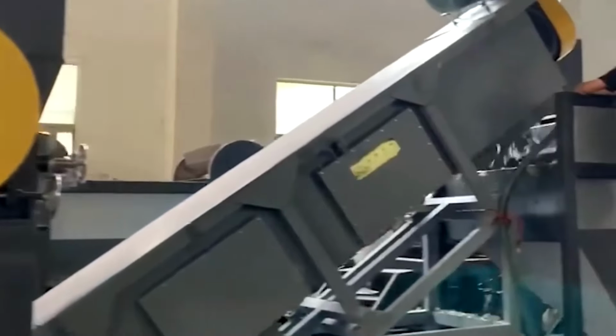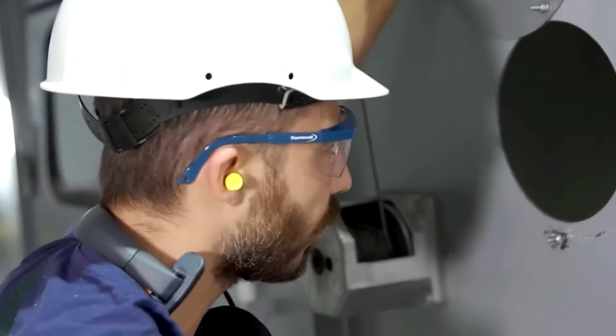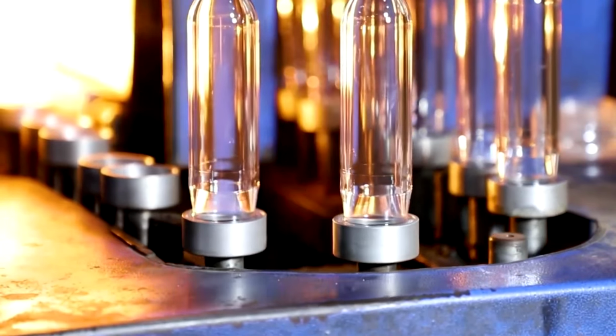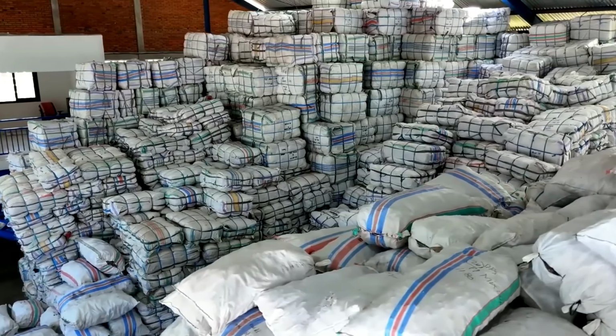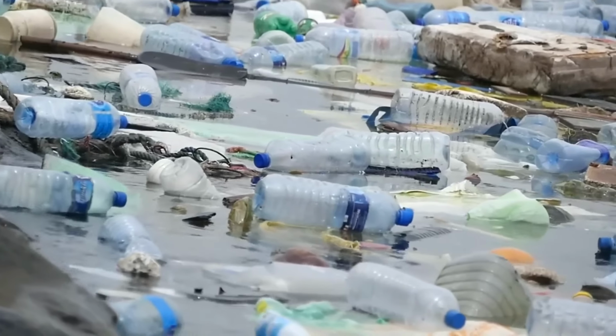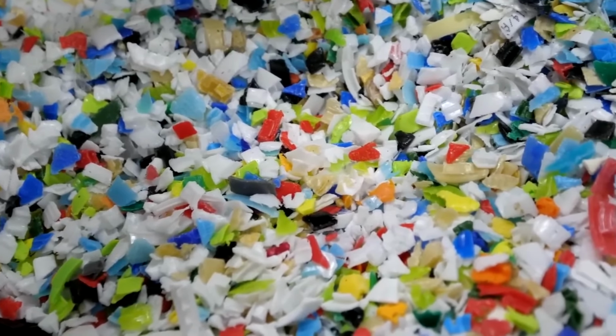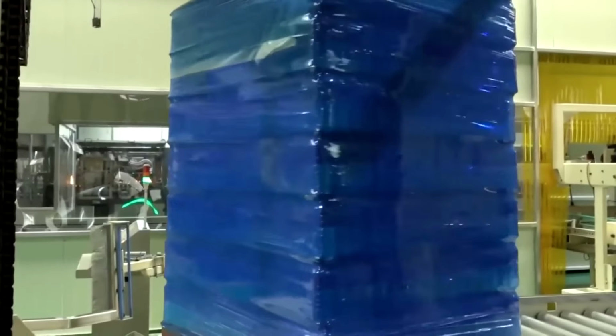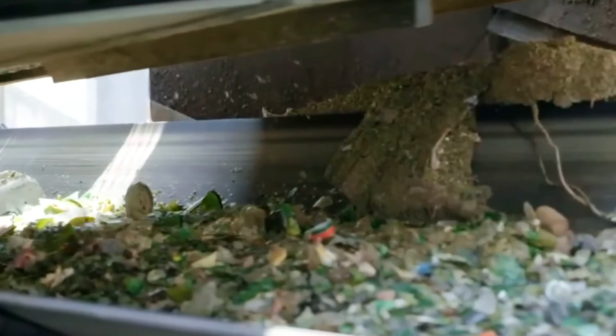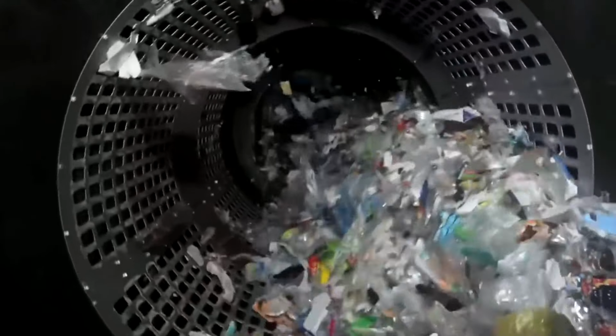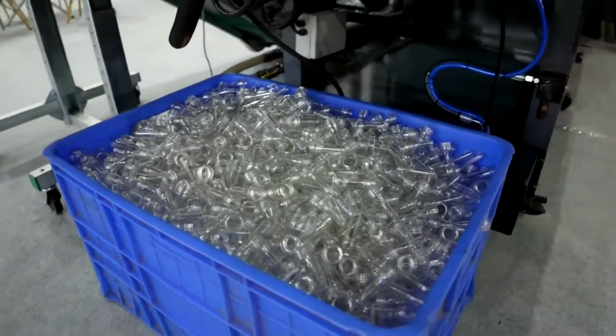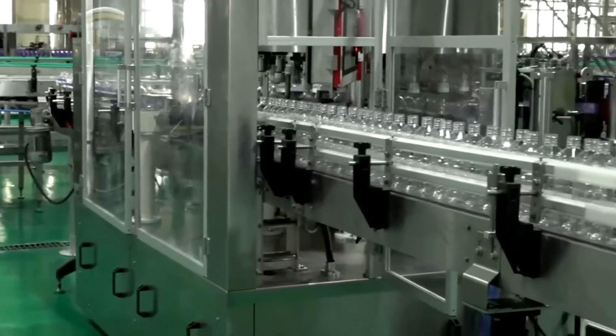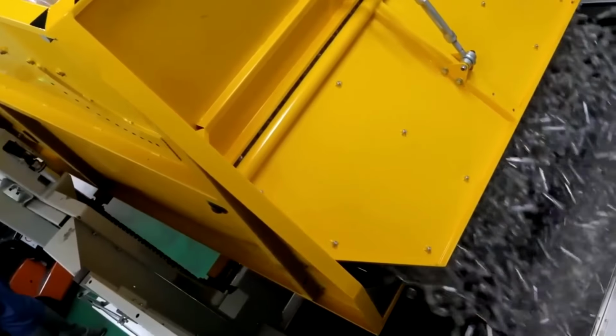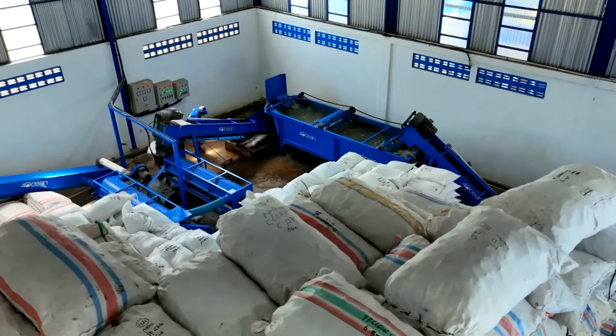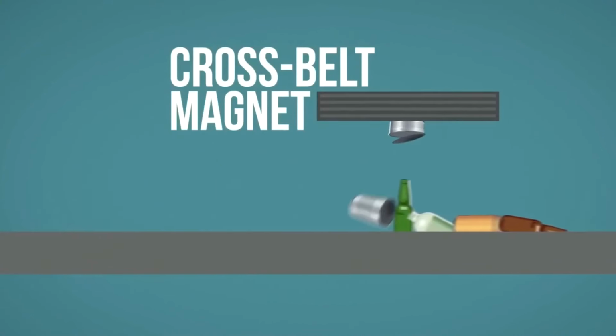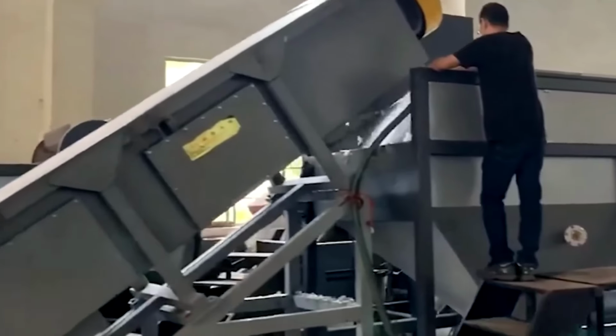The sorting process now shifts from the mechanical to the microscopic. High-speed optical cameras take over, their sensors scanning every individual flake. In just a few thousandths of a second, they analyze color, transparency, and surface texture. A single machine can process over 1,000 fragments per second, achieving an accuracy rate above 95%. The moment the system detects a specific type, a clear PET flake, a green one, a piece of white HDPE or a foreign particle, a precisely aimed jet of compressed air fires, knocking it from the main flow.